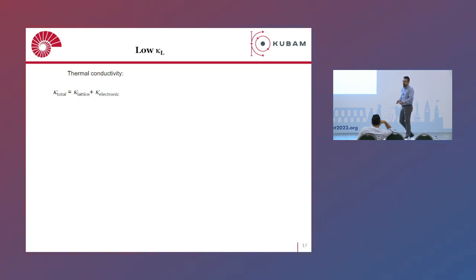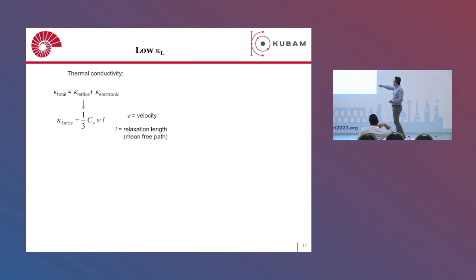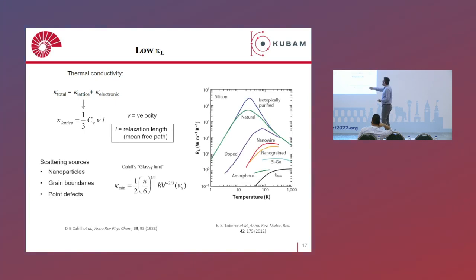Now what about the thermal conductivity? So for thermal conductivity, I told you that the electronic part is connected to the electronic structure through the Wiedemann-Franz law. So the lattice one, you can see here, the lattice thermal conductivity, is dependent on the specific heat times the phonon velocity and the phonon mean free path. So you can lower this relaxation length or the phonon mean free path by introducing different scattering sources into the microstructure, by nanoparticles, by introducing a large density of grain boundaries, and also some point defects.